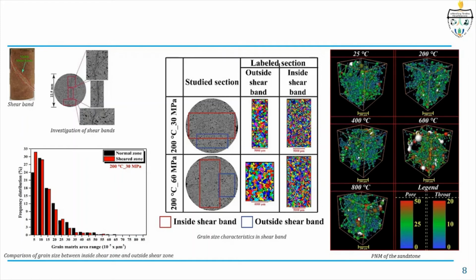The analysis process involved image acquisitions and enhancement, followed by their analysis using image analysis software Avizo. Using such analysis tool, the different phases in the 3D generated volume can be segmented into the matrix, connected pores and non-connected pores and fractures. Intensifying the analysis, the pore network models of the sandstone can be performed for various temperatures and loading conditions, where the pores and throats are being represented as spheres and cylinders respectively, with an equivalent volume of pores and throats in the rock. Increasing temperature illustrated a clear indication of the development of new pores and throats in the rock.